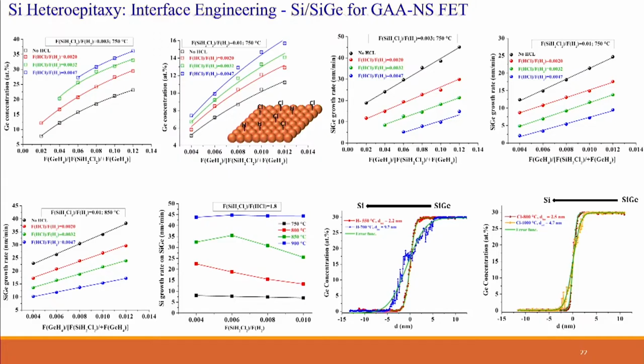We come to the chlorine environment now. With 800, even at 900, we found a really sharp interface, this one. At 1000 degrees Celsius, however, even the chlorine starts dissolving.